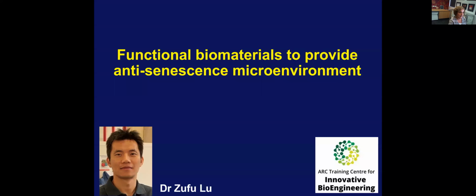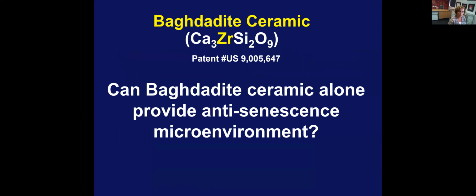Zufu in the lab, he's a biologist, and he asked the question, can these materials that we're developing, the ceramics, provide an anti-senescence microenvironment, partly because of the results of the Baghdadite I showed you and how they induced brilliant bone formation, even in a large bone defect under load without any biologics. So again, in collaboration with my good friend, a maxillofacial surgeon at Shanghai Jiao Tong, we put this material in the critical size defect in aged rats. So we're trying to test it in an aged animal for 8 weeks.